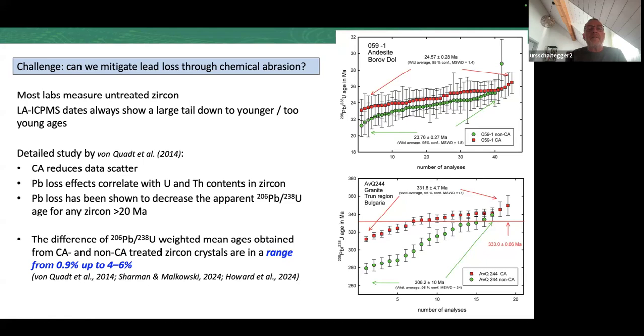There are several studies, but this one maybe is the most complete, of von Quadt et al. 2014. They have measured a series of rocks and established a good data set of non-chemically abraded zircon, in green, and then chemically abraded zircon from the same sample in red. So what do we see? Chemical abrasion clearly reduces the total scatter, and it also removes at least part of this young tail, which goes down to younger and younger ages. And when we take this rock sample here as representative, we can say there is no doubt that in a rock of 20 million years, there is a significant amount of lead loss.